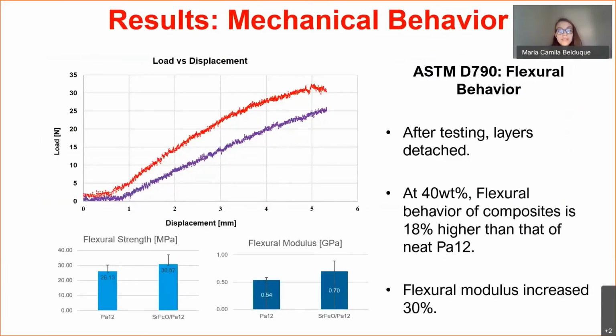After testing, some layers and lines were detached, mostly on the side of the surface and in the middle, but none of the samples broke. The flexural strength of the composite with a 40% loading level is 18% higher than that of neat nylon 12. Additionally, the flexural modulus was increased by 30%. At the mentioned loading level, it can be said that both the nylon 12 and the magnetic reinforcement have a good adhesion, which allows for better load transfer when a bending stress is applied. Therefore, the stiffness of nylon 12 is improved.